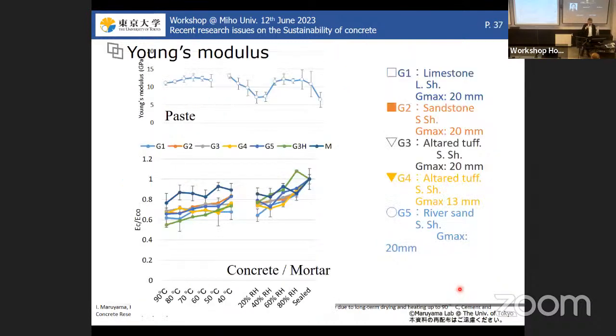So this is the experimental result of the Young modulus of mortar and concrete. I also measured the paste, but I skip it today in detail. In the case of the mortar, we see a decreasing trend, but the difference before and after drying is a little bit smaller than that of the concrete. And anyway, we confirm that the stiffness of the concrete can be deteriorated by only a drying process.